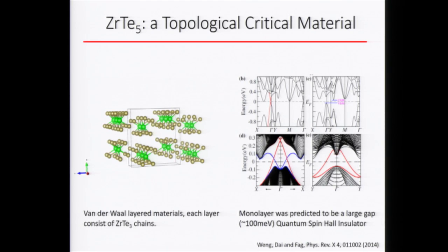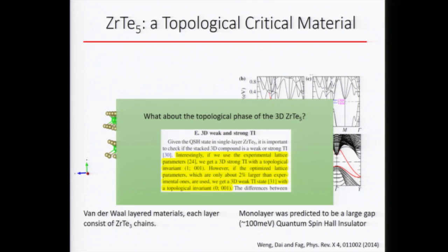It was being studied in the early 80s, and people thought there was a CDW, but later on they actually didn't find evidence of a CDW. But more recently, there's a very important theory paper suggesting that the monolayer of this material is actually a quantum spin Hall insulator, with a quantum spin Hall gap as large as 100 millielectron volts. There's a lot of work trying to prove that it's a 2D quantum spin Hall insulator, and it's still not robustly proven yet. But its three-dimensional form is also quite interesting because it comes back to the same question that I asked early on, which is what happens when you stack a lot of quantum spin Hall insulators together.